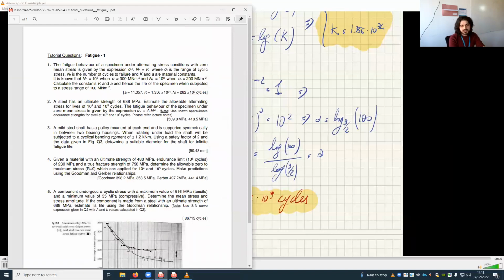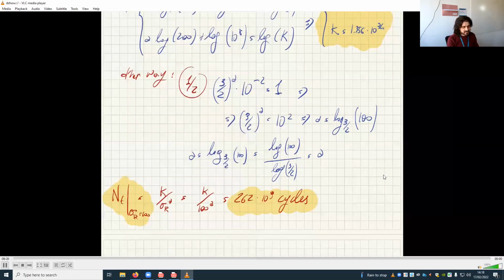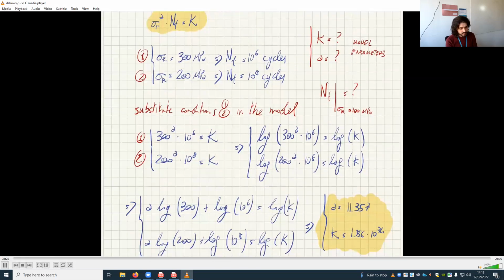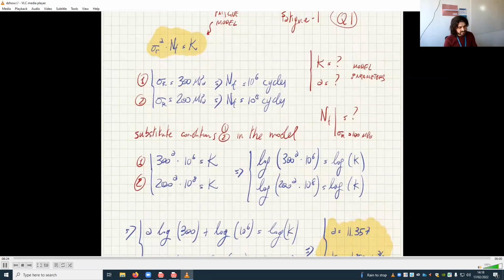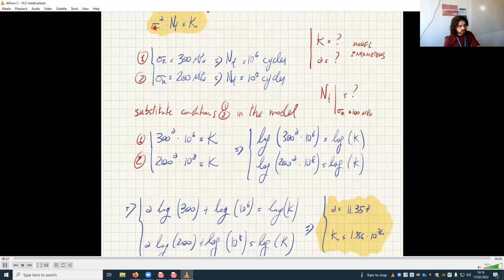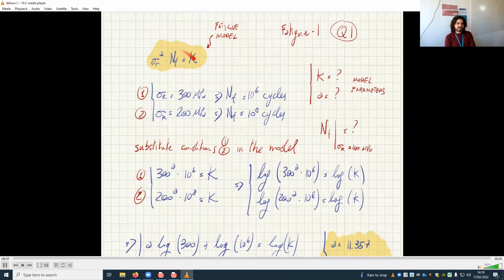Do we take into account the units mega? Well, that's up to you, because these A and K will have different units and will be different numbers depending on what you want to put here and here. So these A and K are just empirical numbers that don't mean anything. Those are just the two numbers that make it work. Experimentally, that's the empirical relationship that you have. So this doesn't come from any elasticity theory, really.